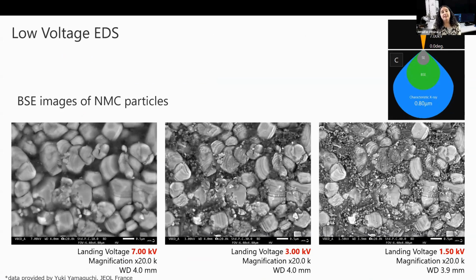So why would we want to analyze lithium-ion batteries at low kV? Here's a quick example of NMC particles from a battery cathode, imaged at accelerating voltages of 7 kV, 3 kV, and 1.5 kV. At 7 kV, the high beam energy penetrates the binder material, making it barely visible. Improved contrast and resolution of the binder are observed at 3 kV, with further enhancement at 1.5 kV, allowing for clearer visualization of the binder structure. Since X-rays penetrate even deeper than backscattered electrons, we would expect to see this same trend in the EDS data as well.